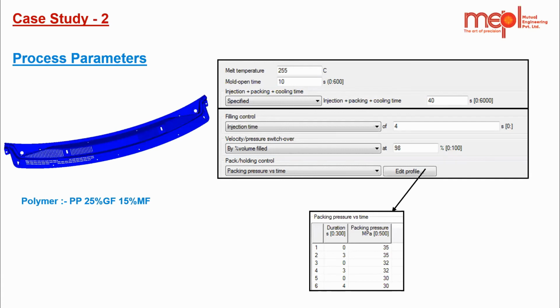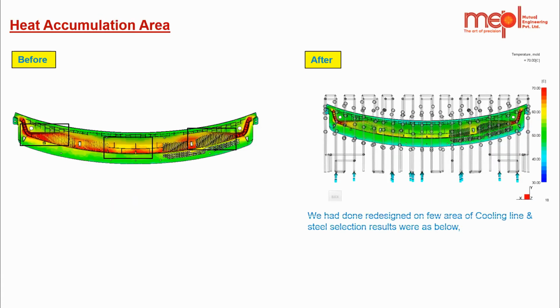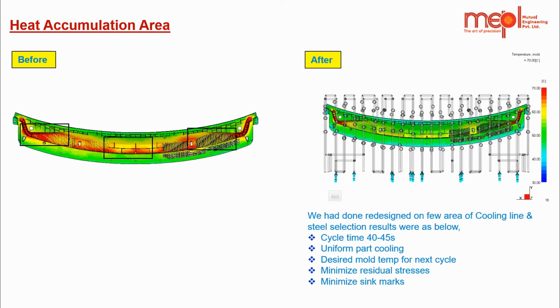In this part we have used material PP 25% glass filled and 15% mineral filled. We used fill-flow-warp analysis, and the parameters for this analysis are as shown. In this area on the left side, we have shown the heat accumulation area, which was very challenging. After that, we changed the cooling lines of the part and modified the cooling.